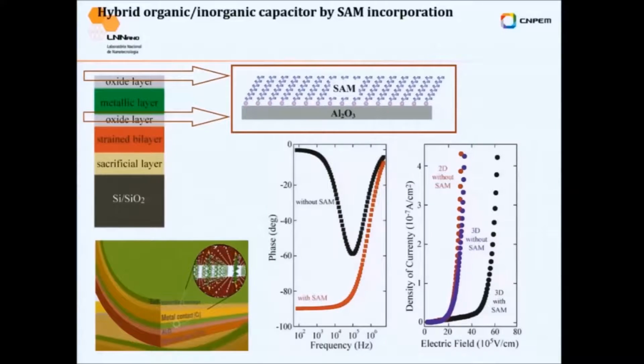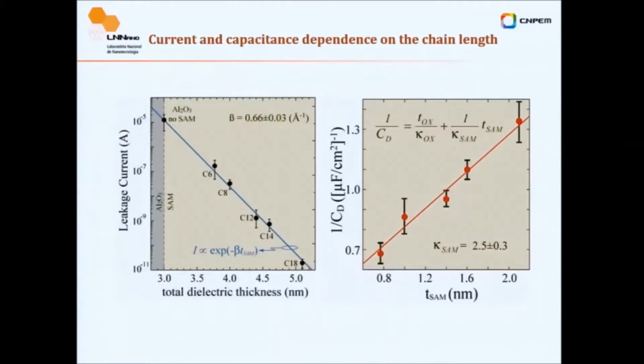So this is what it means, depending on our customer. I'll show this figure, you can say, look, I need more capacitance but not a leak, but I can afford the leakage current. Okay, that's fine. Then you can put basically no molecule, you can put a 6-carbon molecular layer over there, and so on and so forth. And you see you have a very nice linearity. This is typical for tunneling behavior, and you can also tune the capacitance.